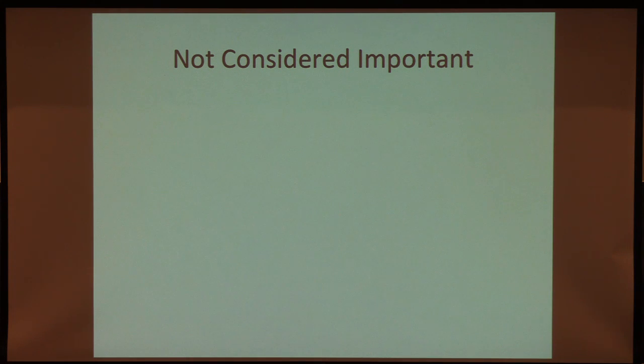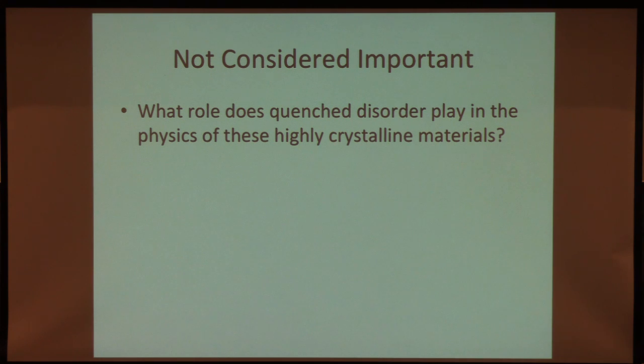I thought it's interesting to note some things that are generally not considered important, which may be wrong. So one thing that's not considered important in the field is the role of quench disorder in the physics of these materials. And there's a strong reason for this, which is that much of the effort in this field, since they were first discovered, has been focused on trying to get better and better and more crystalline and more pure materials so we could somehow get at the essence of the problem. And in fact, a lot of the progress in the field has come from just this progress in material science. We have much better characterized materials, and so many of the experimental facts are no longer under dispute. That does not necessarily mean that disorder plays no role.